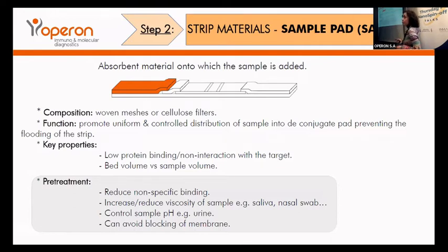The key properties are the same in all the materials. We really don't want interactions between this material and the analyte or the target. So it's important to select a material whose bed volume matches the sample volume that we are going to use. Sometimes it's also necessary to pre-treat the material in order to reduce non-specific binding, increase or reduce the viscosity of the sample, and, mainly if you are working with urines, control the pH.